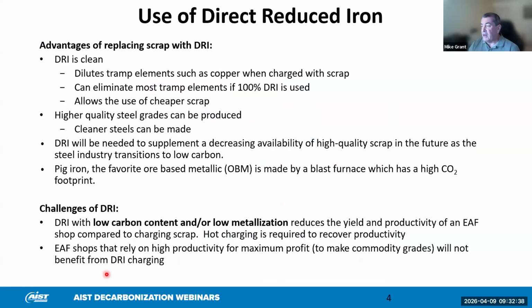So in effect, we're using the DRI to dilute the tramp elements. Copper is the big one that we're trying to reduce. It can eliminate almost all your tramp elements if 100% DRI is used. Cheaper scrap can be used if we mix it with DRI, but in the end, we want to make high quality steel. And with decarbonization trending towards more and more EAF production, there's going to be a lot of competition for high quality scrap, and DRI is going to need to be available to replace that scrap that's being sought after.